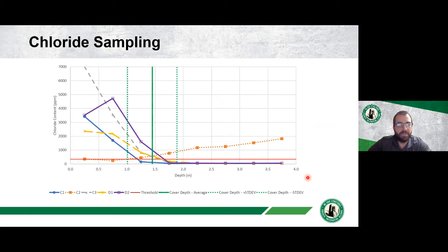Also doing chloride sampling. So here we take in cores from the deck's surface at 0 inches into the concrete section and look at the concentration of chlorides at 1/2 inch increments. You can see here the green lines indicate the solid green is the average cover depth, and then the dotted green lines are plus or minus a standard deviation of cover depth. And then this horizontal red line is the chloride threshold.